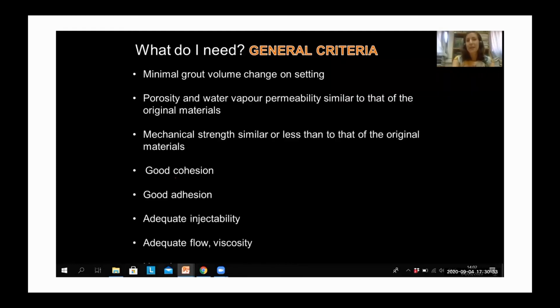So in terms of general criteria, what do I need from a grout? As we said, we want minimum volume change in setting, we want porosity and water vapor permeability which are similar. Mechanical strength, we say we would like it similar or less, because we don't want a repair material which is too strong compared to the original ones. And then what we need, good cohesion, of course. We don't want something powdery behind our painting. We want a good adhesion, because that's the purpose of it. So we need to re-adhere different layers. So good adhesion is fundamental.